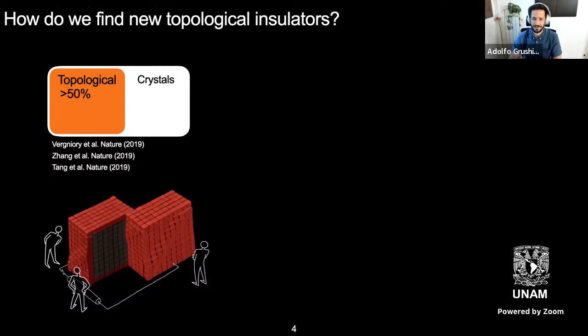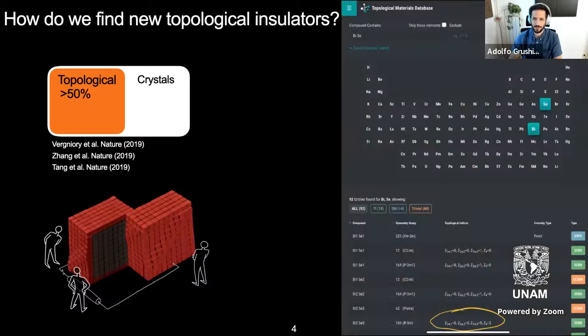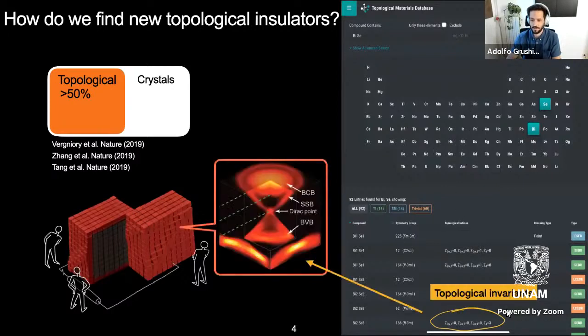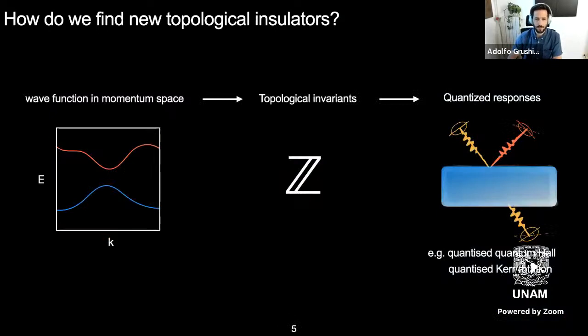Now actually it's relatively easy for a theorist, at least like I am, to go online and click on the elements that your favorite experimental friend is growing, for example, bismuth and selenium here. And in these databases, you'll get some numbers. And these numbers are actually what we call topological invariants. So there are numbers that characterize these phases and tell you whether or not you'll find these topological edge states or surface states at the surface of your material, and what kind of surface states you have.